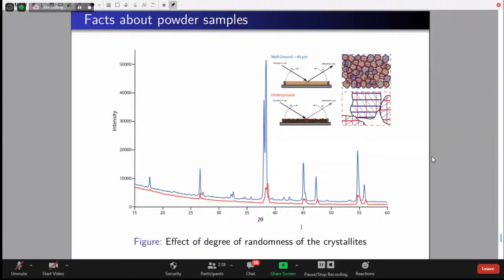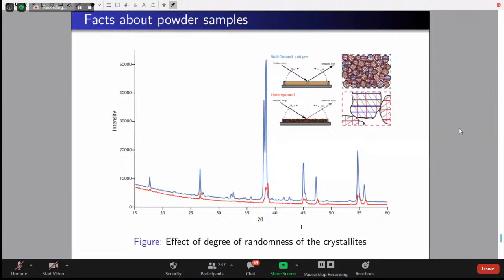So we should use a mortar and pestle and make it a very fine powder before giving it for diffraction. Then there are some very enthusiastic students who grind too much and go below 1 micrometer. Below 1 micrometer, they gain some amorphous content which is not actually in the material, but has come because of the grinding. Then the effects of crystallite size and strain come into the picture just because the student put more effort into grinding. So there should be a balance in how much we grind. That's why people say by touch it should be like talcum powder. Then it is less than 40 microns, a good powder for diffraction.